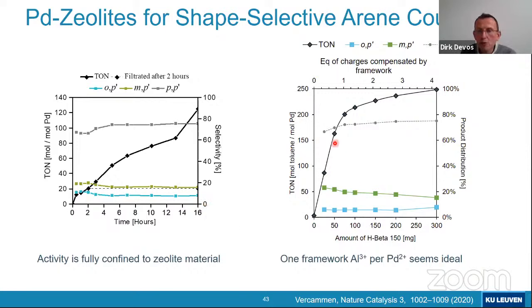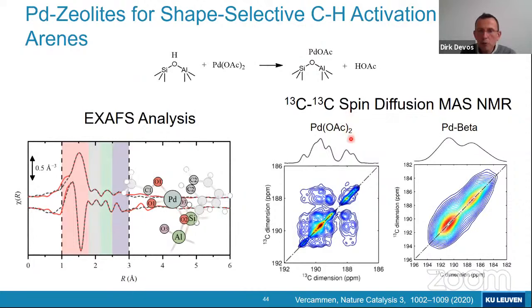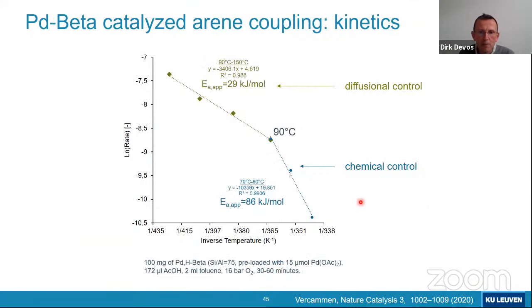We have also looked a lot at how much of the zeolite you need in comparison to the palladium. And then the activity of the palladium increases up to the point where you have precisely 1 aluminum per palladium in the whole system, which means that one of the charges of the palladium is indeed compensated by the zeolite framework. We looked also at the active site, and for instance, with EXAFS, we got considerable proof for such a siting in which the palladium is sitting on the zeolite, with here 1 aluminum. On the other hand, there is still 1 acetate in the neighborhood of the palladium. We have also quite some solid state NMR evidence that I'm not going to discuss, but the idea is just 1 acetate sitting on an isolated palladium.